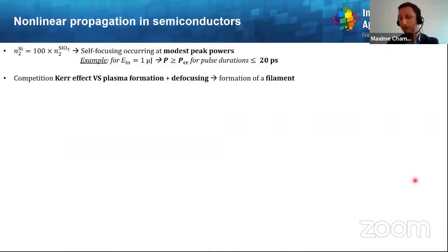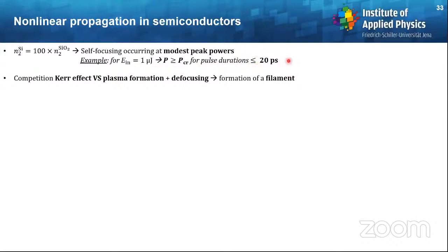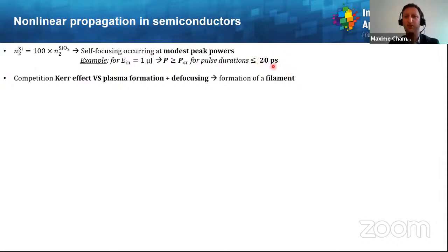When one wants to explain that, one has to recall that silicon is a medium where the propagation is highly nonlinear, for the reasons I mentioned previously about the nonlinear refractive index, which is 100 times higher than that of fused silica. For instance, if you consider 1 microjoule input pulse energy, which is pretty typical, the good order of magnitude for laser processing applications, then the peak power will be higher than the critical power for self-focusing for pulse durations below 20 picosecond. And this value of 20 picosecond is extremely short.